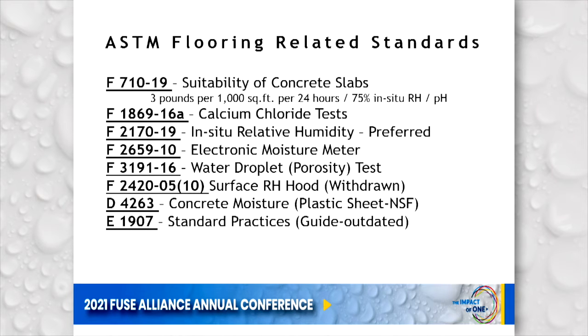I'm going to touch quickly then on ASTM flooring related standards that you need to be aware of. ASTM F710, we kind of touched on earlier. It's the suitability of concrete slabs for the installation of resilient flooring. And within it, we find those benchmark values of 3 pounds per 1,000 square feet per 24 hours, or 75% relative humidity on an in situ test based on either a calcium chloride test or in situ relative humidity. So the calcium chloride test is F1869. The most recent publication date was in 2016. F2170, most recent publication was in 2019.